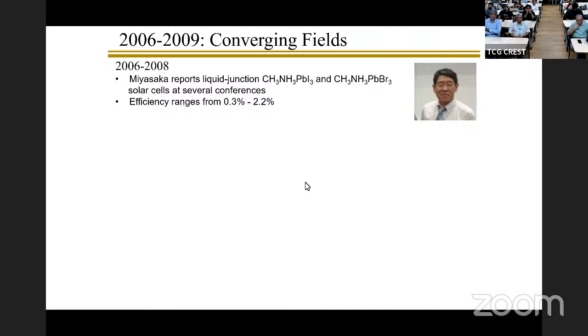The reason he was interested was that he knew the band gap of this material is on the order of 1.5, 1.6 electron volt. And that's nearly the ideal band gap for getting the maximum power by absorbing solar light. Because of course, for every photon that is absorbed, you create an electron and hole. If this electron and hole do not participate in any other process, but go to the outer circuit to drive a current, then for every photon, you get 1 unit of current. But of course, the power is not just the current, but current multiplied by voltage.